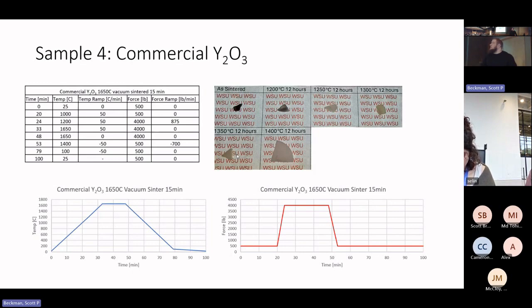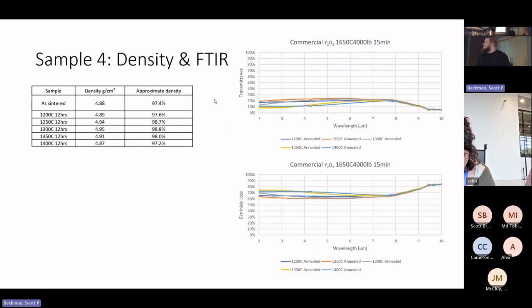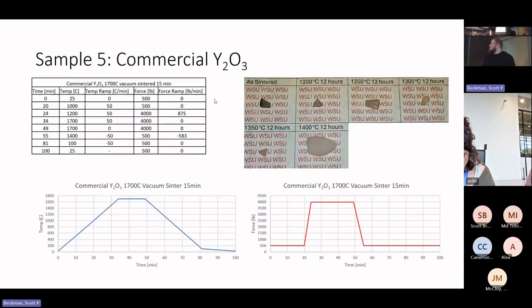And then as we go on, we see 1650 degrees C, 15 minutes of annealing time, and we see again some transmittance, but not quite as much. So these samples were not quite as well sintered and not quite as well densified, and you can see that corresponds in the transmittance data.